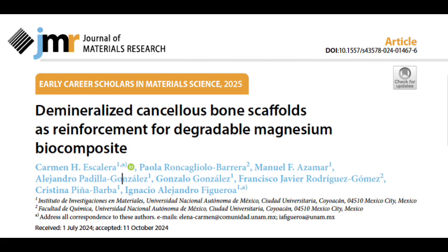I would think a thicker layer would make it stronger. You'd think so, right? But it's not just about how thick the layer is. It's about how well it bonds everything together. Okay. So in the composite with the carbon coating, the one with the thinner layer, that one had a much stronger bond between the magnesium and the DBM, like a really tight seal. Exactly. So a thinner layer actually made it stronger. In this case, yes. What about the other composite?